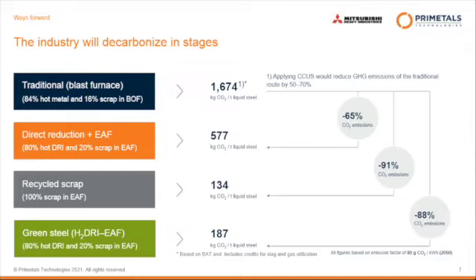To move towards steel now, actually the big challenge is to transform the traditional integrated steel producing pathway, where we still stand, the best figures are 1.7 ton of CO2 per ton of steel, including already the credits from various gases and slags. And so we will see a phased approach, most likely.